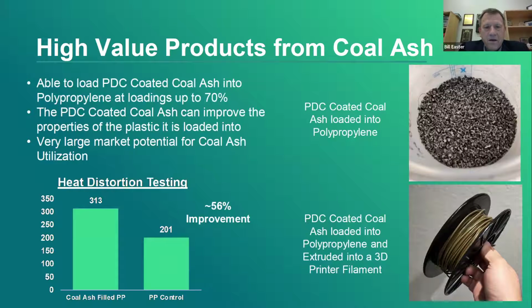Taking the coal ash and putting it into plastic, we picked polypropylene. It's one of the two most known, most used plastics. Amazingly, if you typically buy polypropylene, you can get 30% mineral filling of it. We were able to put in 70% by weight. So you can imagine using a recycled polypro, which again is incredibly inexpensive, with fly ash,